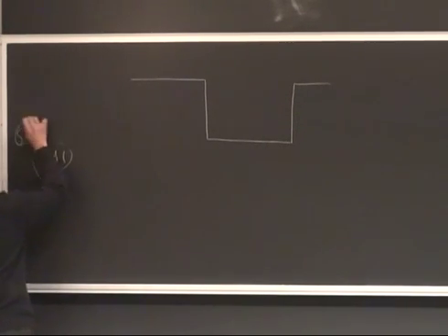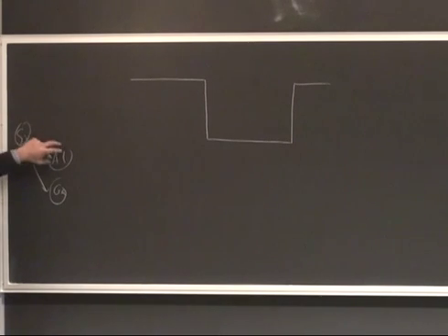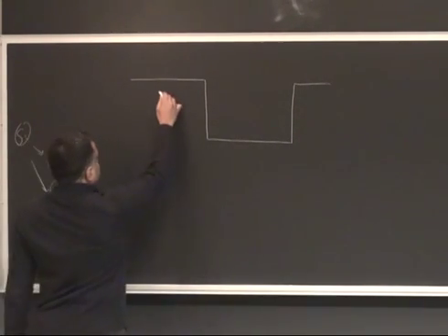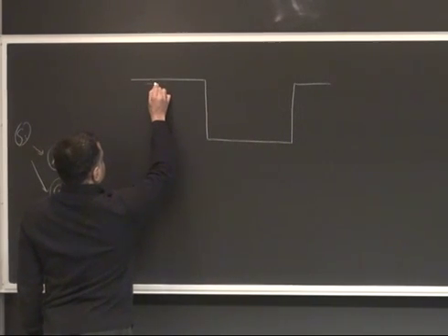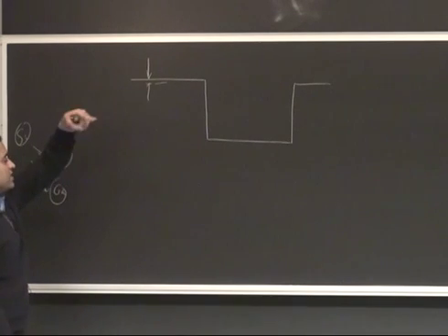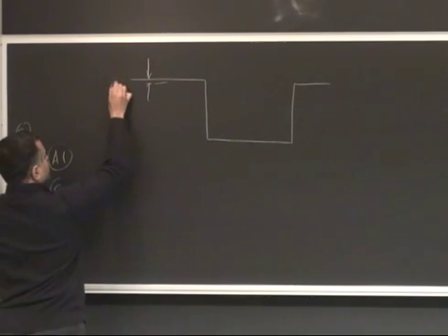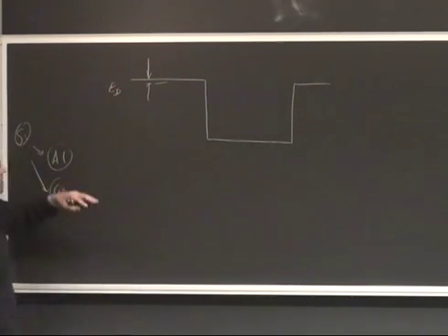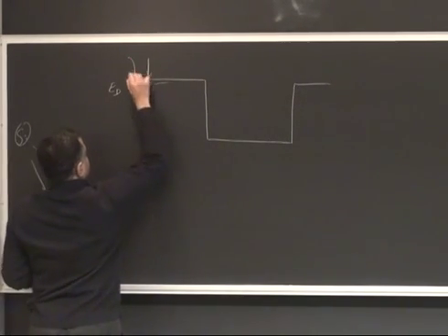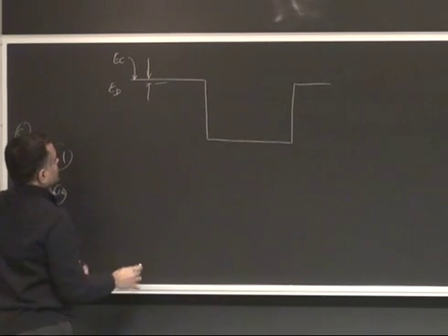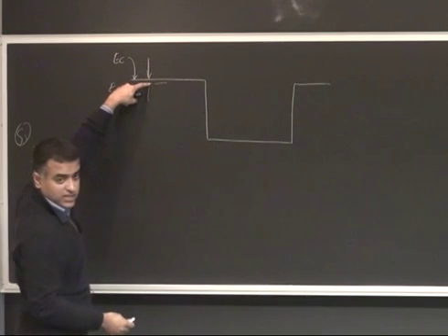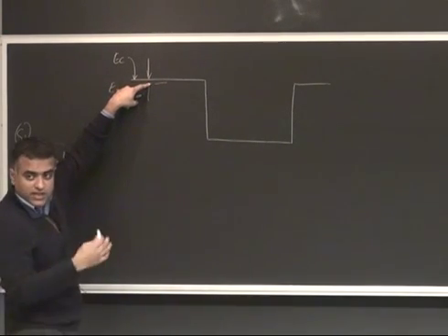So silicon replaces some of these atoms, and it has one extra electron than either aluminum or gallium, which have 3 in the outermost orbit. And the end result of that is if I put dopants here, the dopant energy level, the electron energy level corresponding to the dopant, is a certain donor ionization energy below the conduction band edge. Okay? So that's the picture you have in mind. This is the conduction band edge, and the extra electron that's tied to the silicon is sitting here at this energy level, slightly below that.